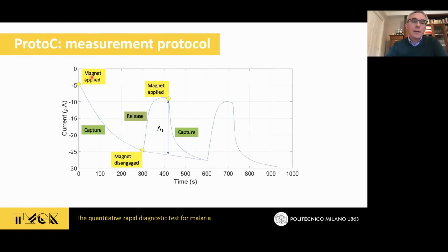So we approach the magnet, there is a first capture, and the current decreases because the impedance is increasing, up to 300 seconds and a bit more. At this moment, we take out the magnet. The reason is that this initial decrease of the signal is also superposed to some drift that you can't really control. But at this moment, it's like a trigger. So you disengage the magnet, there is a sudden release of the particles. They are no more attracted, they start falling down again. And so there is a signal increase here. You measure this amplitude in this way, and this amplitude will be proportional to the concentration of the particles